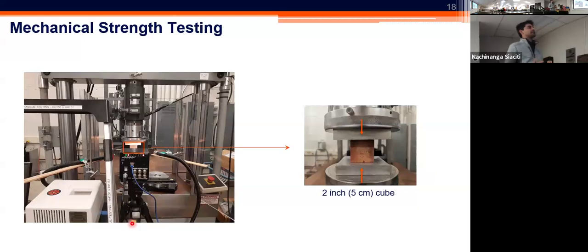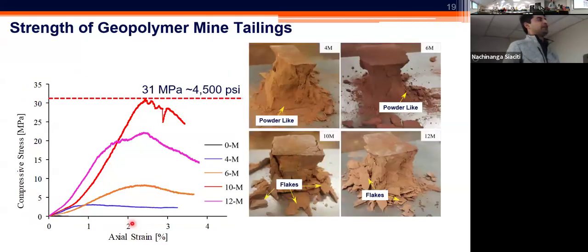So what do we do with these bricks that we make? Well, the first thing we do is evaluate the compressive strength of these samples. What you see on this picture is a compression test, where these bricks are placed between the platens and subjected to uniaxial compression. Then we can evaluate and document the performance. We found that the strength achieved is highly linked to the molar concentration of the activator, in this case the sodium hydroxide activator. What you see here is a typical trend: with the increase in molar concentration, we often see an increase in compressive strength. And the strength can be as high as, as shown here, 4,500 PSI or 30 MPa.